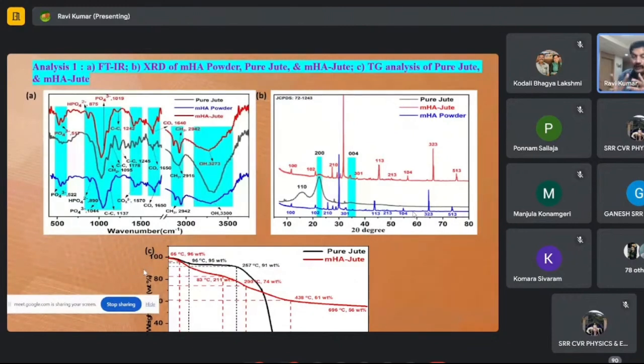It means that only when we heated this material for a prolonged time was it decomposed slowly, because the surface is shielded by the MHA. The MHA stops the penetration of oxygen and heat waves. That's why this is called heat release rate. We confirm it here.